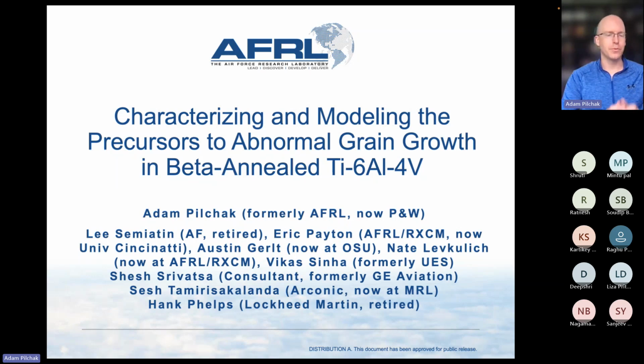So the issue was that several airframe structural components were forming these abnormally large grains once they went into the beta-annealing process. And the grains are huge, like the size of your thumb, or maybe even two of them in some cases. And so as everyone knows, large grains tend to be bad for strength and fatigue properties and things. And so we were called in to try to understand what the source of that issue was and how we